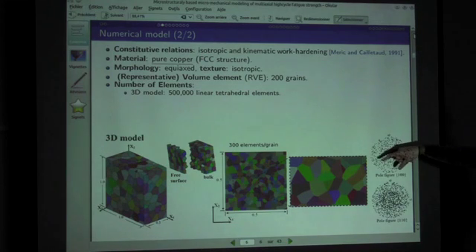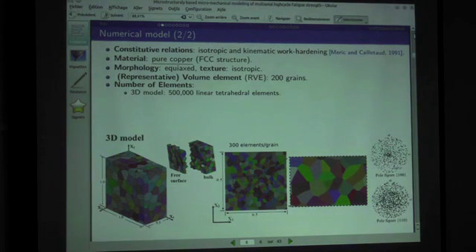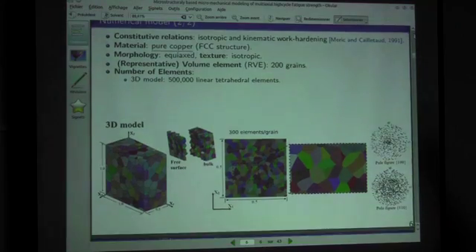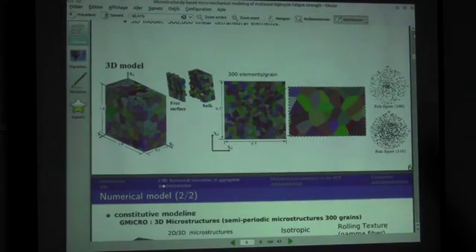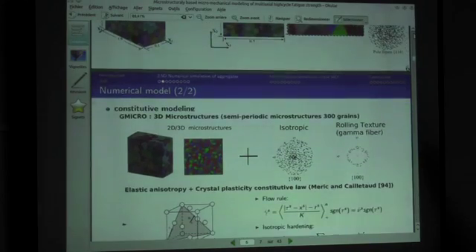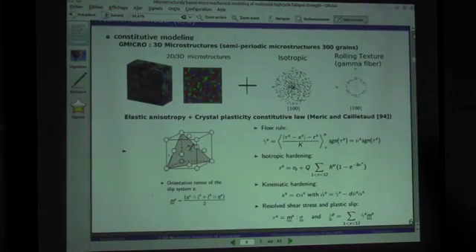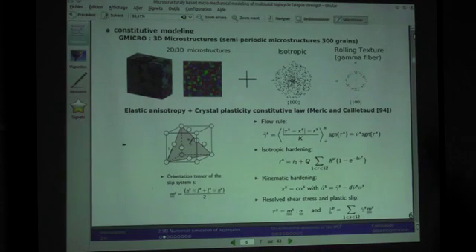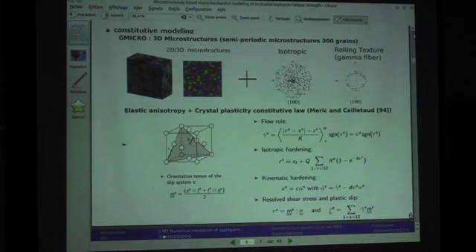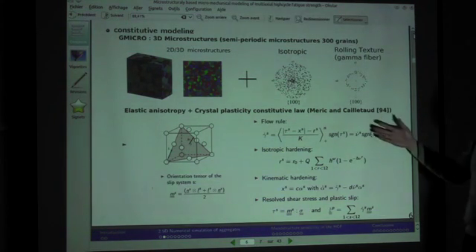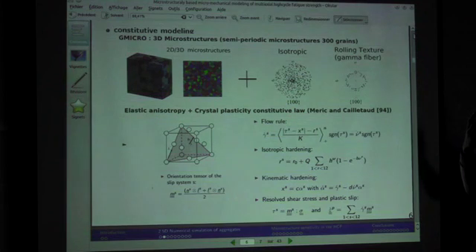And then we put in those computations different textures to evaluate, for example, the effect of textures on the fatigue properties. So we can model the microstructure explicitly in terms of geometry, and we input the textures we want, and then we use adequate standard constitutive modeling for crystal plasticity. For those who are not much aware of it, it's more or less using the standard constitutive laws, but projected at the grain scale on the slip systems of the material.